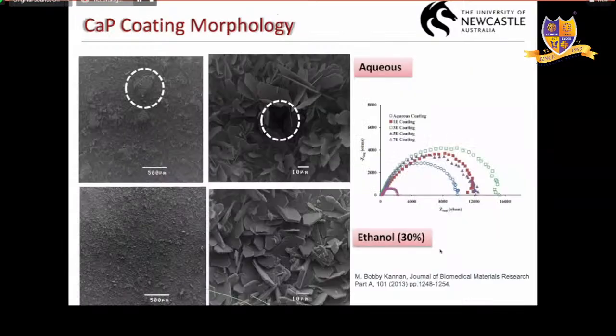But more importantly, look at the morphology of the coating. With an aqueous-only solution, you have these porous structures. And as we say, having a coating with a porous structure is worse than not having a coating, right? So you don't want this kind of morphology. With the addition of ethanol, it created a much more densely packed coating in this case. And the resistance is also high.